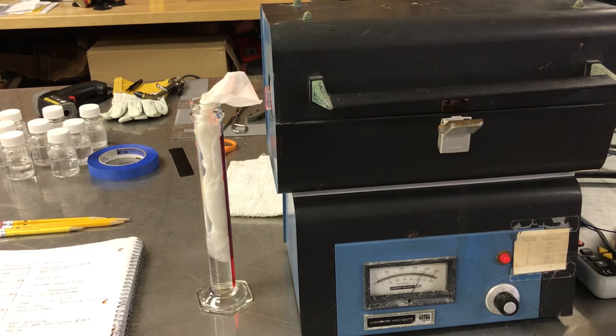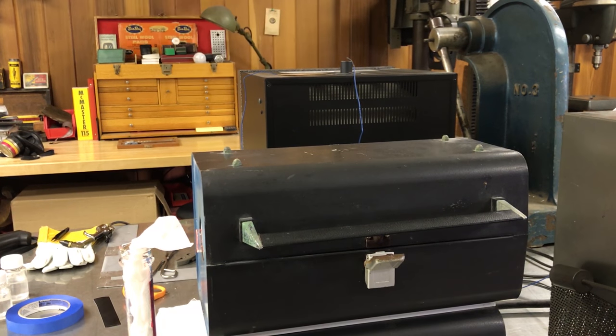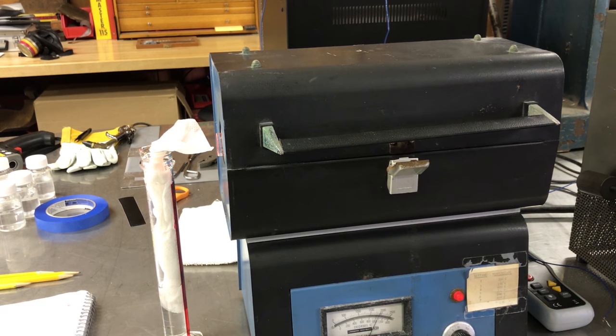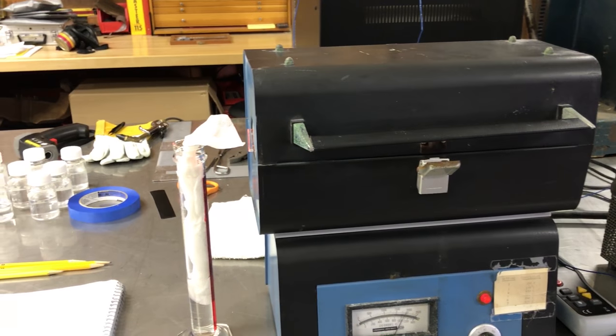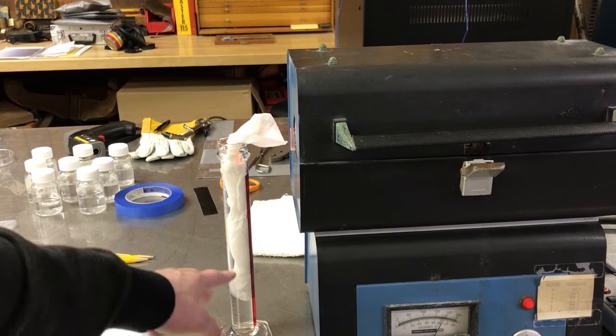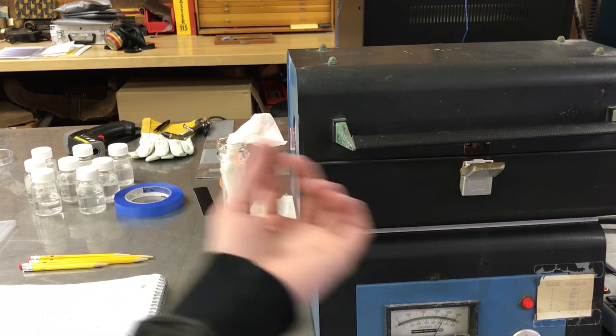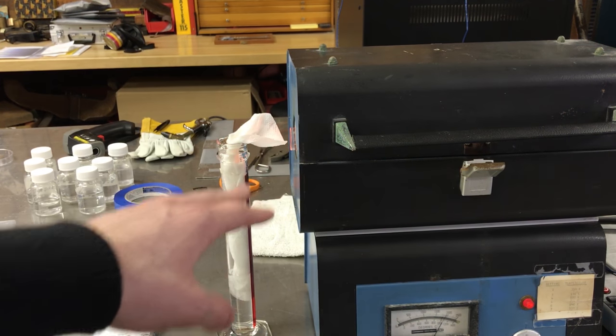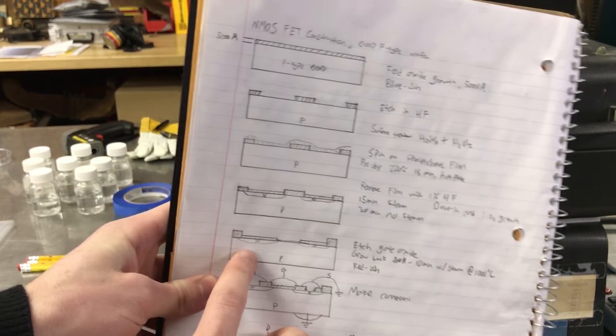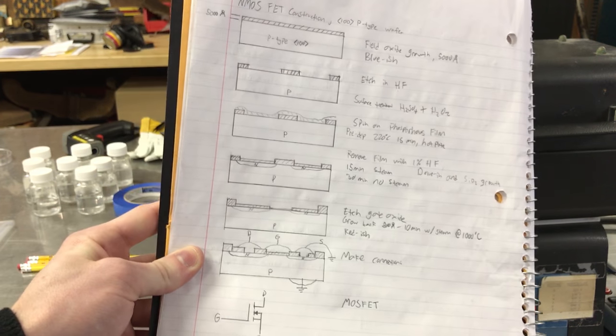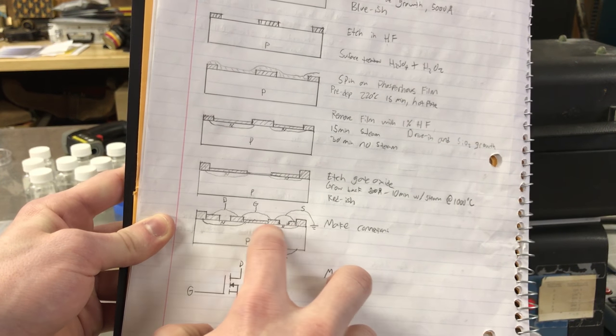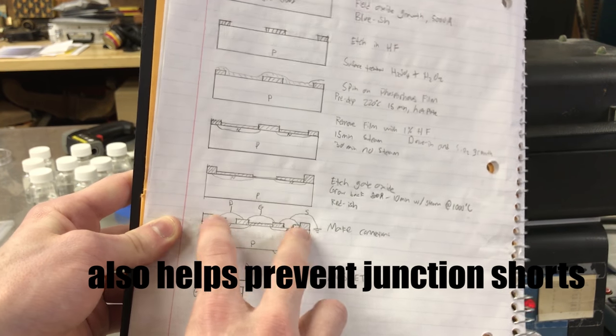I forgot to mention, when you're doing the field oxide step, to make the oxide grow a lot faster you can pump steam into the chamber. There's a few ways of doing that. For that furnace back there, I have that access port in the top. So I would actually drip water into that and then it would instantly vaporize and create a water vapor atmosphere inside of that furnace. For this tube furnace, if you have a steamer for fabrics and curtain, you can blow it through the chamber along with the nitrogen gas flow. An alternative way that works alright is to take a water bottle or a graduated cylinder and then put a paper towel into it and put it very close to the opening of the furnace. And it will wick and draw that water in and the moisture content will be a lot higher in the furnace. Now I'm doing this during the diffusion step so that it grows a small or a thin oxide layer on top of our N-type wells here while it's doing the diffusion. And the reason why I'm doing that is because later it allows me to etch small windows into that oxide and it allows me to be more precise about where I connect my drain and source electrodes to on the bulk of the wafer.